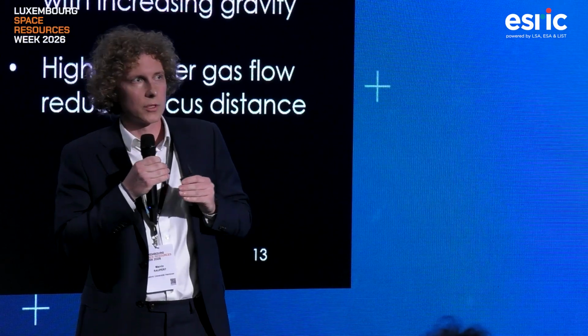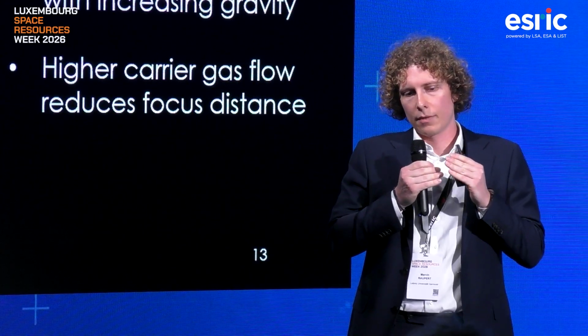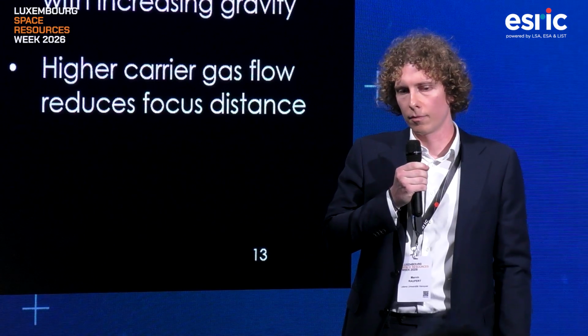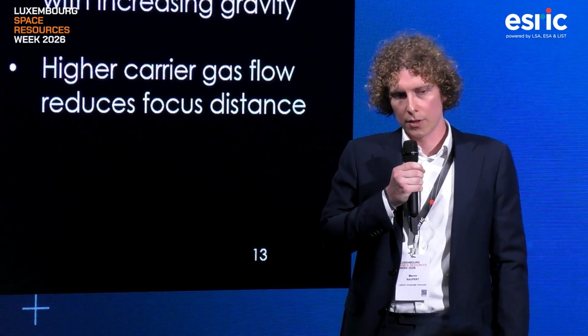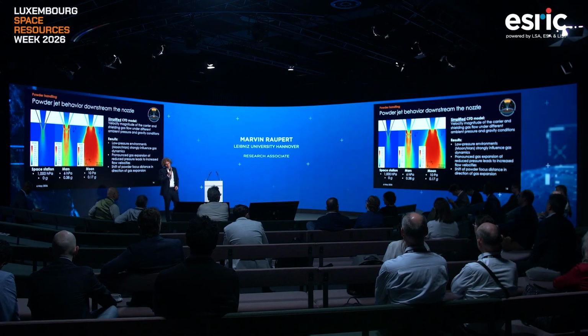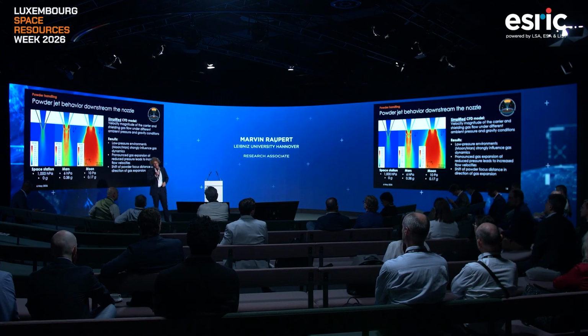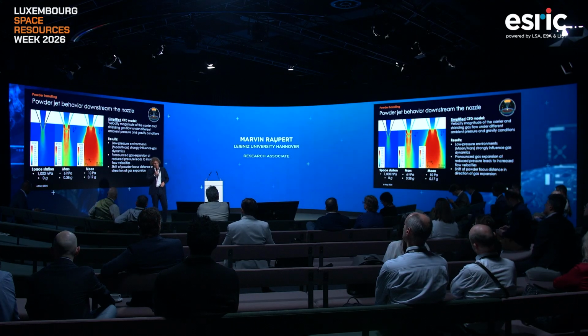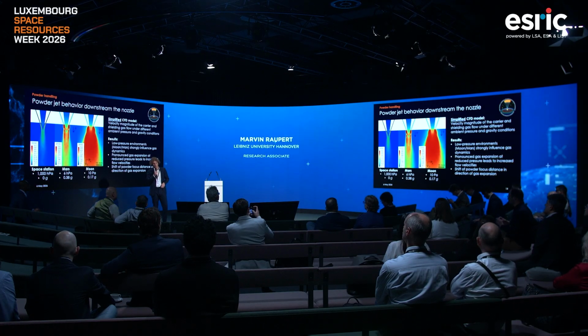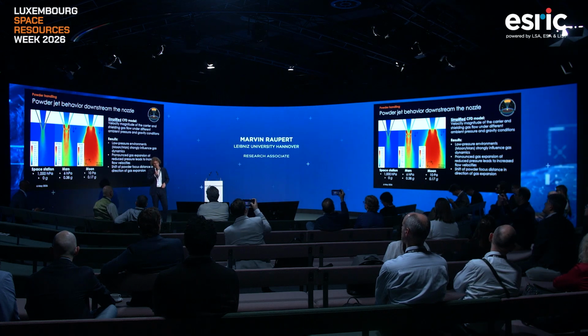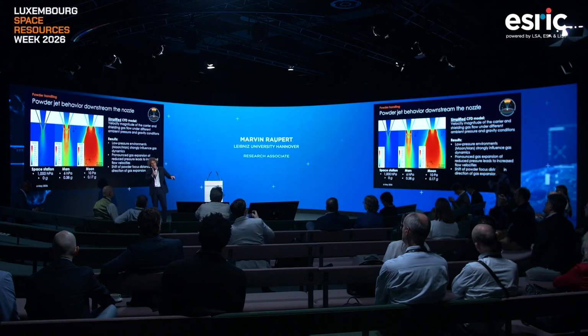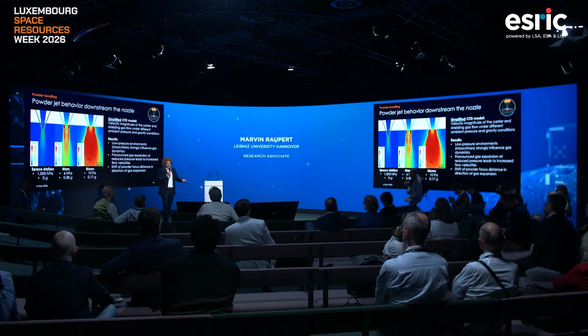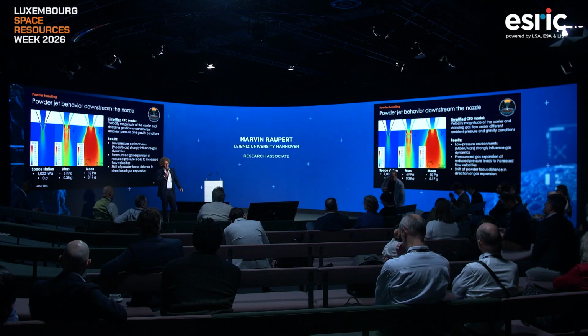But the influence was so small that it was still in the area of the manufacturing zone of the powder nozzle. So that is not a huge problem. But if we have a closer look at the ambient pressure, then we could see that this has a huge impact. So the powder focus distance has a shift in the direction of the gas expansion. Here we simulated this with a simple setting for a space station with normal pressure, microgravity, Mars conditions, and lunar conditions.